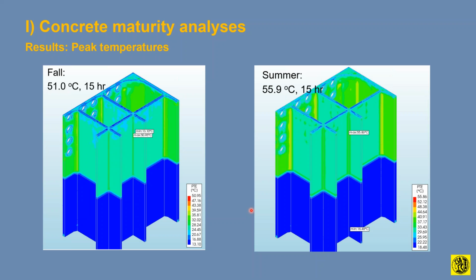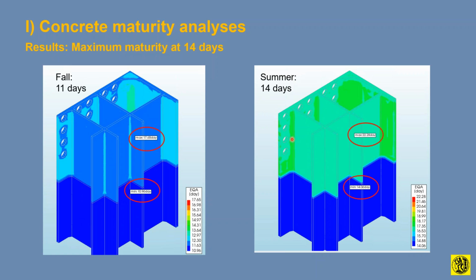So if we do the peak temperature studies, we got out of this solution: in the fall, the caisson generated, in this area here, 51 degrees centigrade at 15 hours, and then 56 in the summer. However, in terms of maturity, we looked at the maturity gain out of this analysis. Diana can give us maturities during actual time conditions. So we looked at the maturity of the concrete at 14 days after casting, because at 14 days, more or less, was the age where the submergence phase came for the caisson, the installation phase for the one that failed.